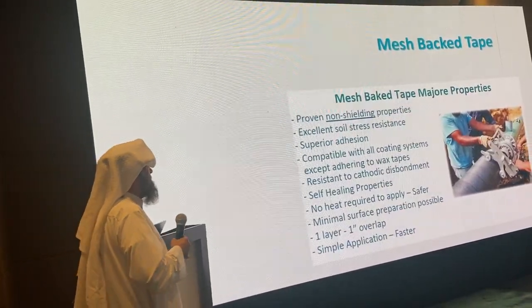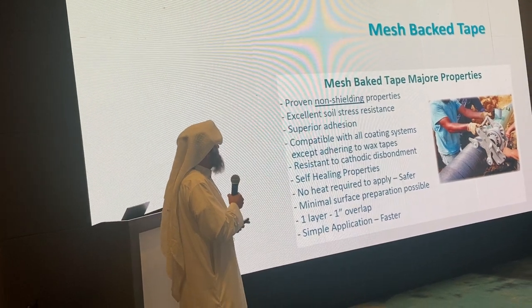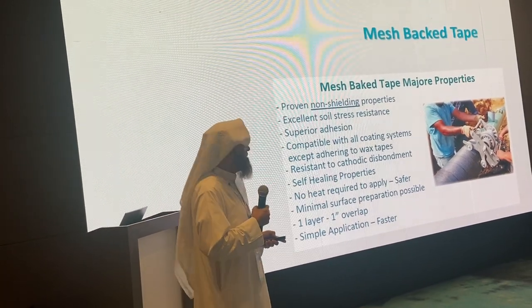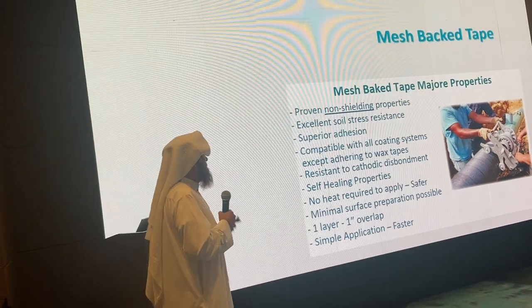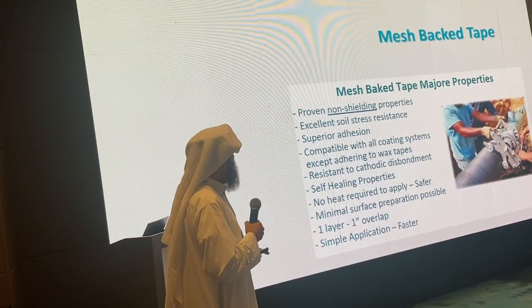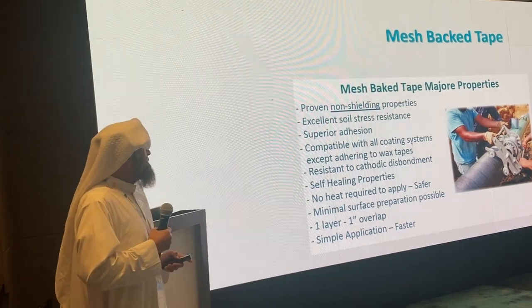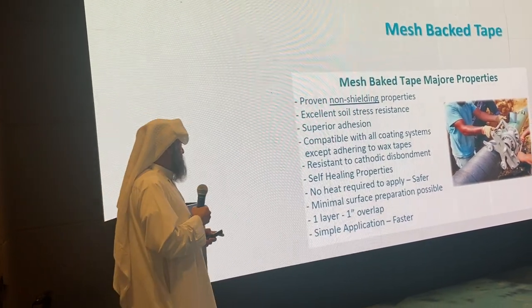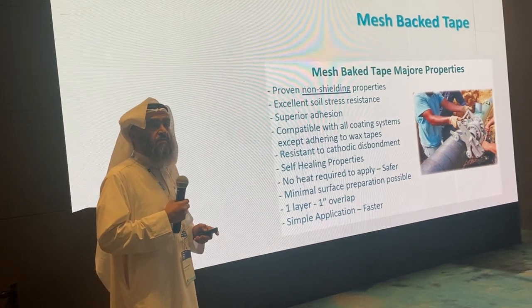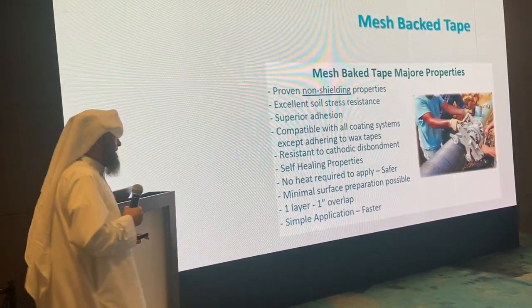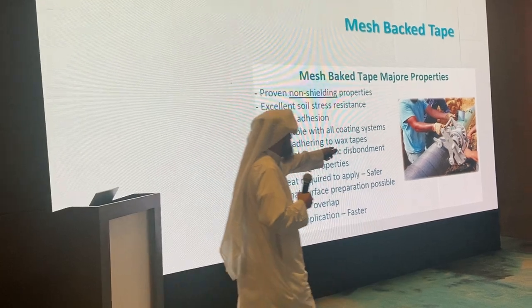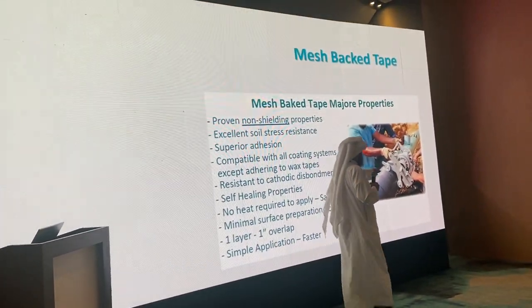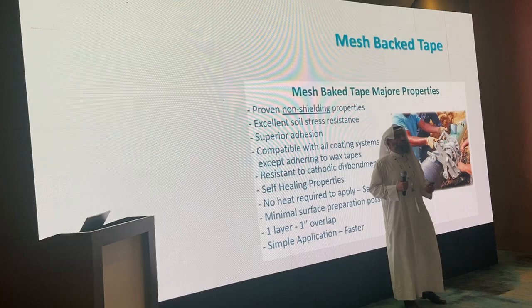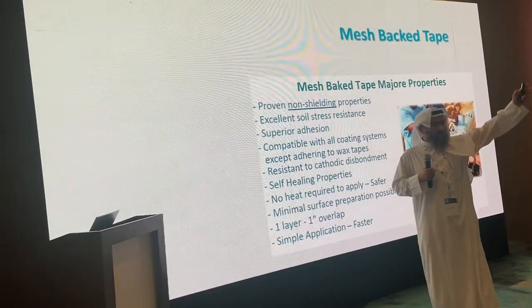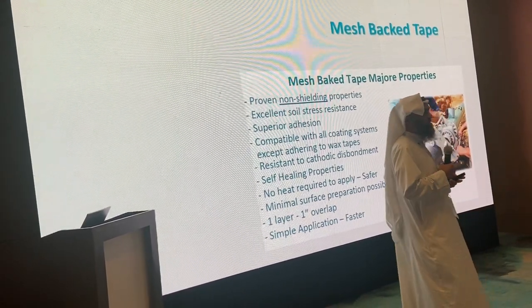So what is mesh-backed tape? It has proven non-shielding property, excellent soil stress resistance because of strong adhesion, superior adhesion, compatible with all coating systems, self-healing property, no heat required, minimum surface preparation, only 1 inch overlap, so it saves money, and finally it is very simple to apply. You need a manual wrapping machine that maintains a strong adhesion. If it is a very long pipeline for rehabilitation, we can use a machine-operated wrapping machine.